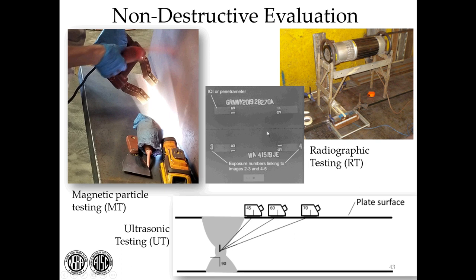That's a very nice assurance of the welds that we produce. They're tested with either X-ray or UT or phased array, as I'll discuss in a moment, and that tells us that if a situation like this does occur, we'll find it, and we can make sure that we get that cleaned before the bridge is constructed. If something like this is discovered in a weld, the fabricator must fix it and then go back and test it again to make sure it's clean.